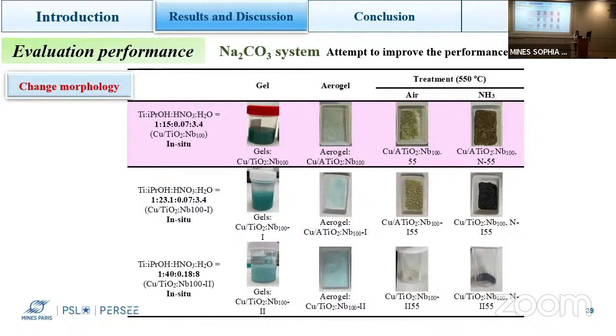I think in my lab we don't put the same volume as the solid, but the same volume as the porosity. Yes, because in fact we try to put the solvent inside the porosity. So we make the calculation because we have some value of porosity, of pore volume. So we add exactly the quantity corresponding to the pore volume, in fact.